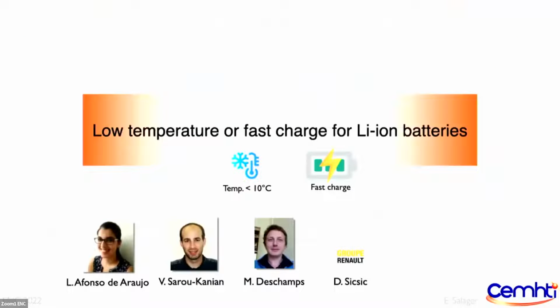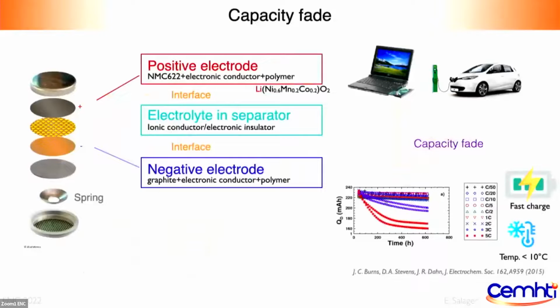And so for the remaining time of my talk, I would like to show you what we've been doing for Ludivine Afonso's PhD thesis on the subject of low temperature and fast charge for lithium-ion batteries. So this is also something where we have really high kinetic issues. And so in this case, what is happening is that we get a capacity fade as we increase the charging rate or as we lower temperature.